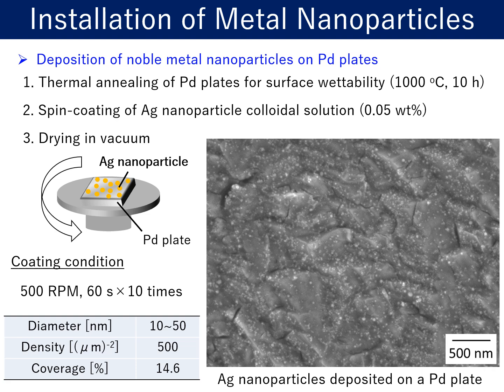To produce the plasmonic energy focusing effect, we implemented noble metal nanoparticles on the surface of the palladium plate before the experiment. We spin-coated a colloidal solution of silver nanoparticles with proper surface pretreatment and drying procedures. In the SEM image, relatively high-density silver nanoparticles on the palladium surface are observed, and we can expect not only the plasmonic field enhancement effect on the planar palladium surface, but also the nanoparticle and nanogap effects.